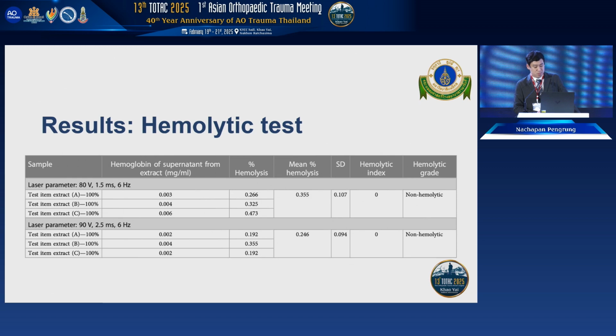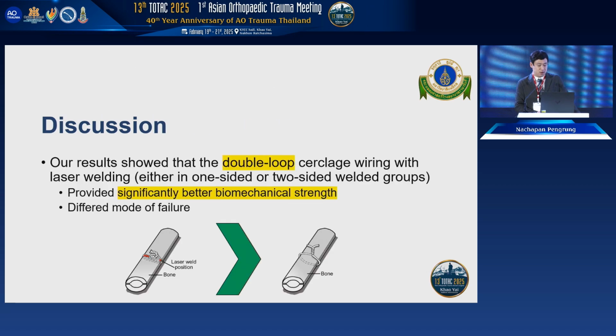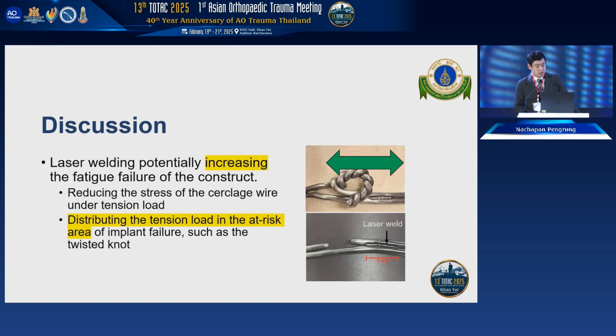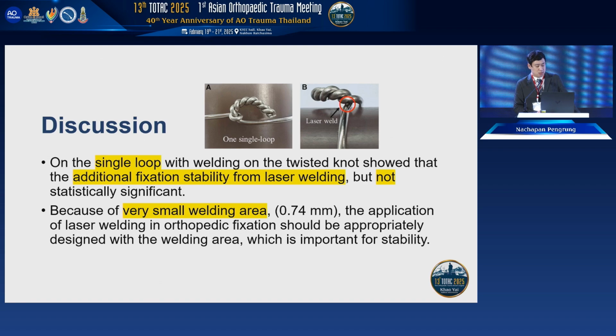The hemolysis test showed a mean percentage of all specimens of less than 1%, so there is no hemolysis. In the discussion, our results show that the double loop with laser, either one or two sides, provides better biomechanical strength and has a different mode of failure compared to conventional. We think that the laser increases the biomechanical property because it reduces the stress on the wire and distributes the tensile load over a larger area. However, in the single loop groups, it also adds stability but not significantly. We think that's because of the very small welding area, about 0.7 millimeter. So we may design another technique for welding in the single loop.